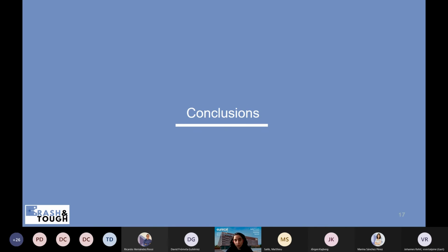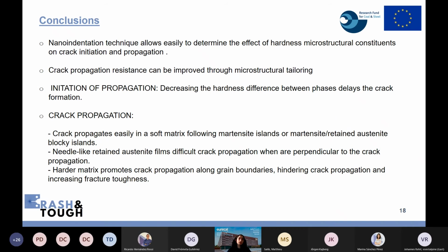So to conclude, the main conclusions are: nanoindentation techniques are an easy and fast way to evaluate the effect of the microstructural constituents on crack initiation and propagation. Crack propagation resistance can be improved through microstructural tailoring. Regarding crack initiation, the main conclusion is that decreasing the hardness differences between phases delays the crack formation because local formability is improved.